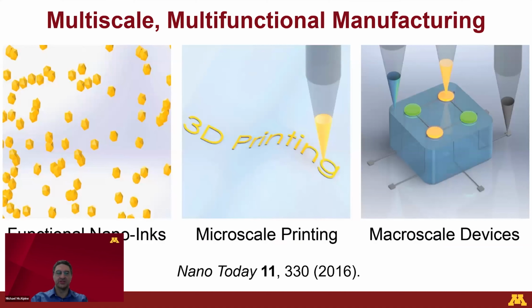So you may be asking, what kind of resolution can we print? And that's shown by this middle image here, which basically is, how well can you force material through a nozzle? What size is the nozzle? And really that's going to be limited to about 10 to 100 microns at the lowest end. It's really difficult to have a nanometer sized nozzle that you can force material through without clogging or breaking. So typically we stick to the 10 to 100 micron resolution range of the actual printing process itself. So we call this microscale printing, but the ink itself can actually go down to the nanoscale. You can have functional quantum dots or metal particles. That's where we get our semiconducting functionality from. So the ink can be at the nanoscale, and then you print at the microscale.